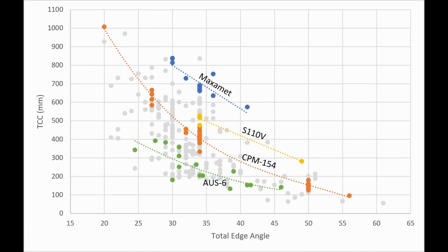To illustrate just how important the edge geometry is, I have a chart here showing a whole bunch of steels versus total edge angle. So if we take the angle that we sharpen on both sides, so 13 degrees on one side, 13 degrees on the other side, that's a 26 degree total angle. And I have highlighted a few specific steels here on this chart. So Aus6, that's a Japanese steel with about 0.6% carbon. If it has a 27 degree edge angle, that's 13.5 degrees per side, it cut about 400 millimeters of cardstock. This matched the performance of CPM 154, which is significantly more wear resistant. It has over 1% carbon.